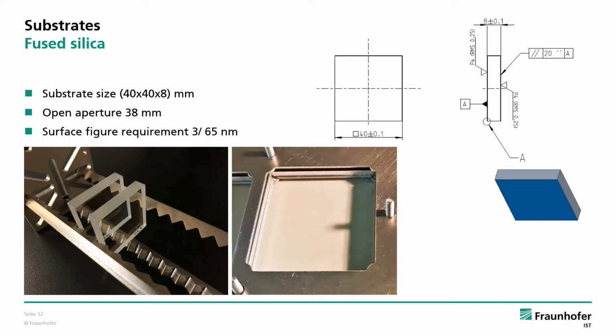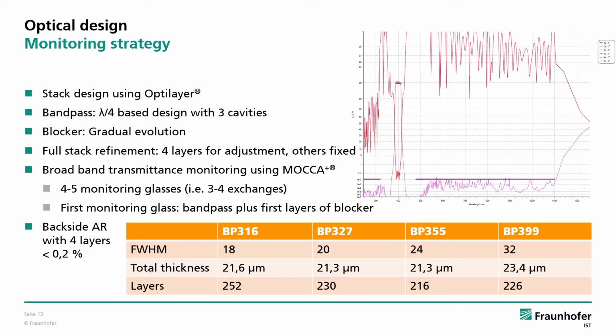For this reason, the substrates were lying only on the edges during the deposition in sputter-up configuration. Besides P4 polishing, the surface figure requirement was below 65 nanometers. The optical design of the layer stacks was made using OptiLayer. At first, a bandpass based on 3 cavities in a quarter-wave thickness design was calculated. Then, the blocker was designed by gradual evolution with an anti-reflection range around the bandpass wavelengths.